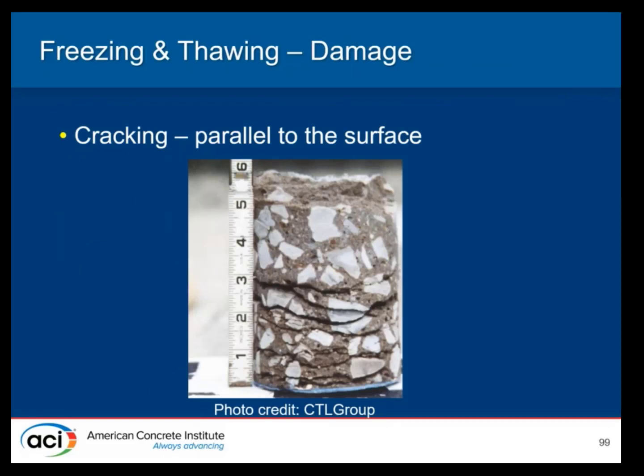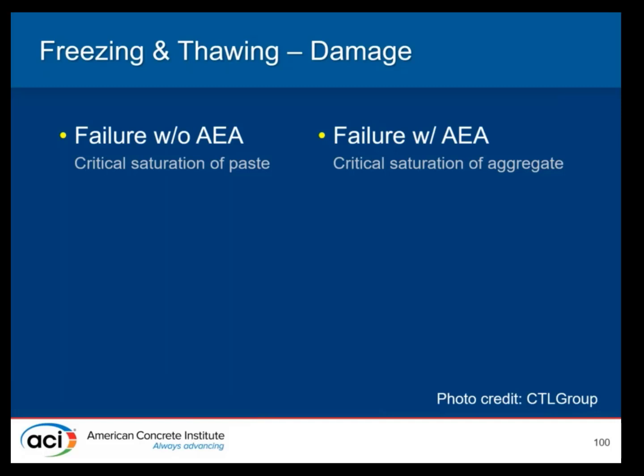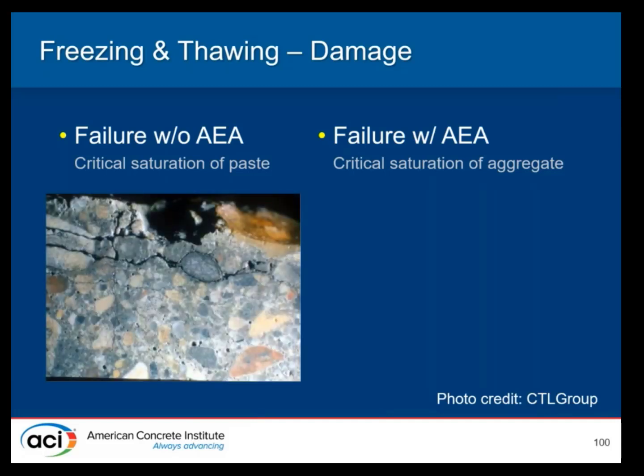So the typical failure pattern in a non-air entrained concrete is, remember we were talking about the water is expanding and the water's inside the paste. As that expands, we typically will get this cracking parallel to the surface, as you can see in the slide. And that occurs after the paste has become saturated with frozen water. Okay, so a couple photomicrographs. This is failure without air-entrained concrete. There's critical saturation of the paste.